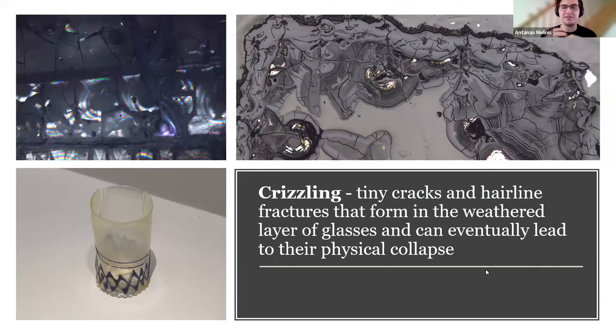So during the later stages of this, the glass can take on a hazy appearance, such as this medieval cup pictured on the left. And this is caused by thousands of tiny cracks that are formed within the hydrated glass layer, as seen on the microscopic surface and the cross-section photographs on top. And it is known as crizzling, using the word in a very narrow sense, as just one of the series of stages that begin with glass weeping and end with complete glass body collapse. And it's a very disfiguring process, as well as very damaging to physical integrity, because it's extremely hard to conserve.